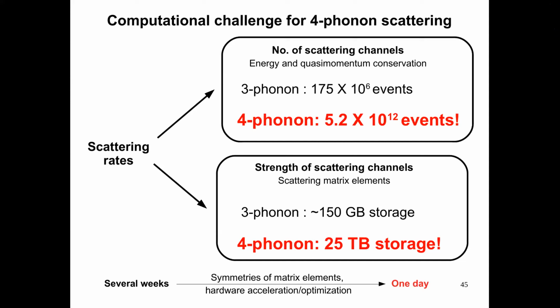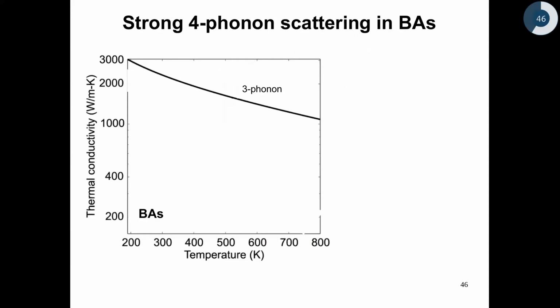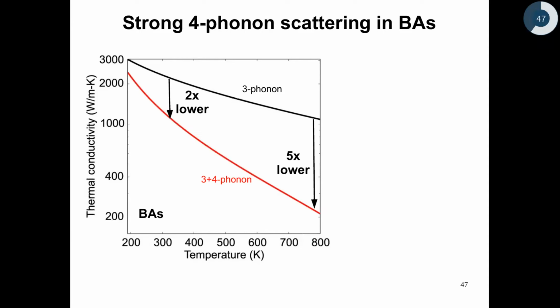So having spent so much effort trying to improve the speed of the calculation, let's see if it's worth it or not. So here, just to refresh your memory, I'm showing the thermal conductivity of boron arsenide calculated using the 3 phonon conventional picture. So you can notice that at 300 Kelvin, the thermal conductivity exceeds 2000 watt per meter Kelvin. That is almost as high as diamond. If I include 4 phonon scattering, what happens is there's a dramatic decrease in the thermal conductivity from the 3 phonon value. In fact, at room temperature, you see that the thermal conductivity goes down by a factor of 2, and at higher temperature, it can go down by a factor of 5.